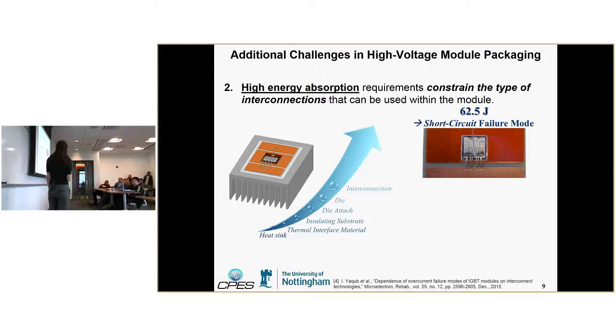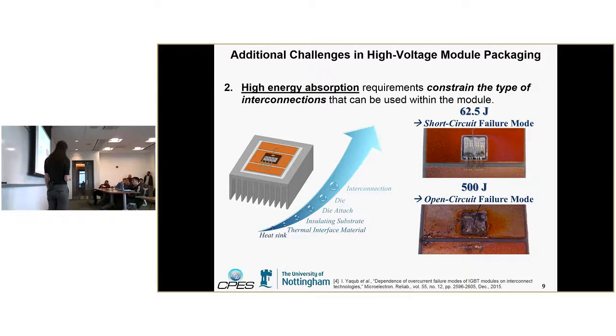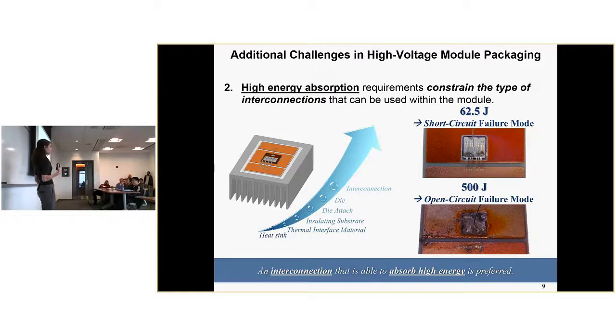So at maybe 63 joules, the wire bonds here are still intact. You increase that to 500 joules, and you can't even see the wire bonds anymore. They're completely gone. And now that's an open circuit failure mode. So that's not always optimal for certain systems. So that's something that also needs to be considered when looking at higher power applications.